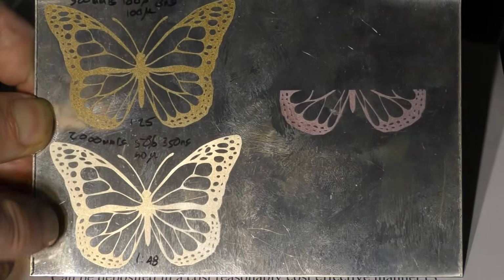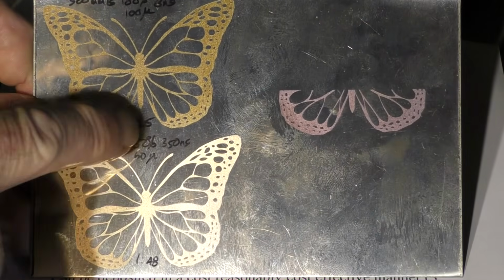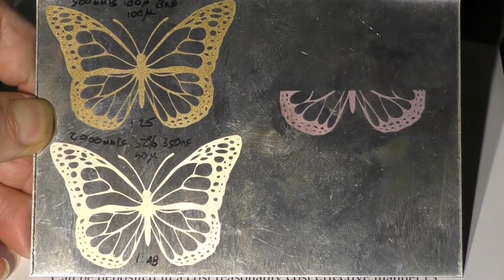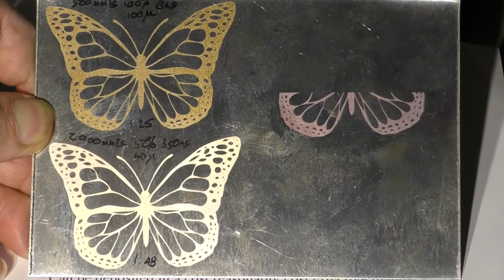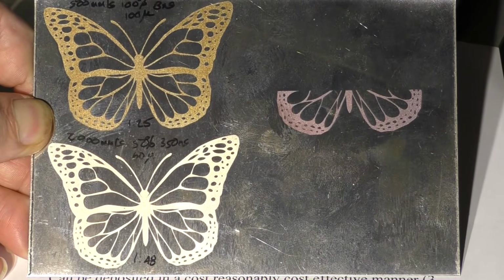I had to give up on this mauve image after about half an hour because that's as far as it had got. Well, here the gold and the white or latte colour, we've got 1 minute 25 and 1 minute 48. Now they're completely acceptable production times for an object that size.